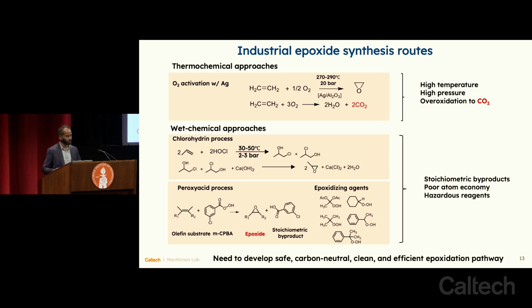We typically start with an olefin, react with oxygen, and make, for instance, ethylene oxide as a product. So this is a very conventional route. If this were the reaction, I would really have no qualms. This is done at just 270 to 290 degrees centigrade and 20 bar of pressure. But the issue is that a lot of this ethylene oxide over-oxidizes. It doesn't stop there as a product. Instead, we continue to oxidize, going all the way to CO2 as a product. And this, in part, is why epoxide production has the 5th largest carbon footprint of any chemical that we manufacture today. It's because of this over-oxidation. So it is really important that we find ways of eliminating this carbon footprint.